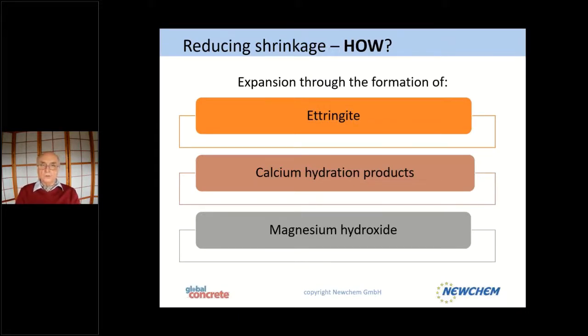So how can we reduce the shrinkage? Now, the standard procedure is to use products which make ettringite needles. With these, you can counteract the shrinkage of your cement. Some people use calcium oxide, which forms different hydration products. This is going through a solution product. We know that Lafarge has used systems with sulfates, calcium oxide or hydroxides, to produce these ettringite needles, these hydration products. We have now also introduced magnesium oxide, because in China people are using a lot of magnesium oxide in dams because they realized that the dams would not crack if they add some magnesium to their cement.